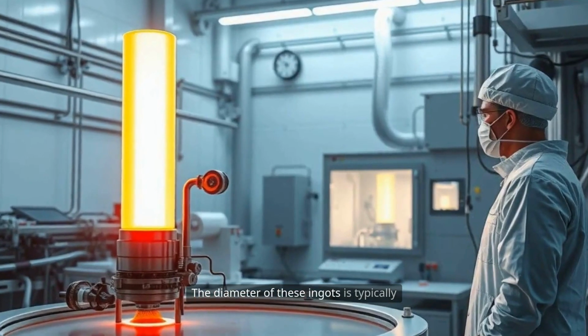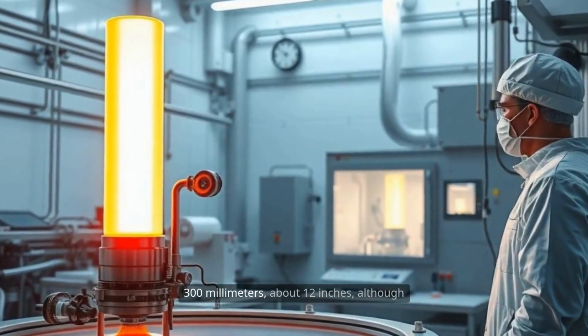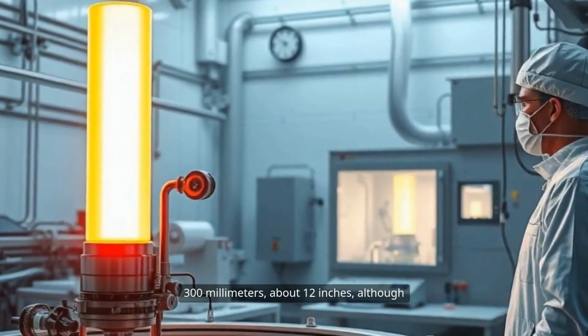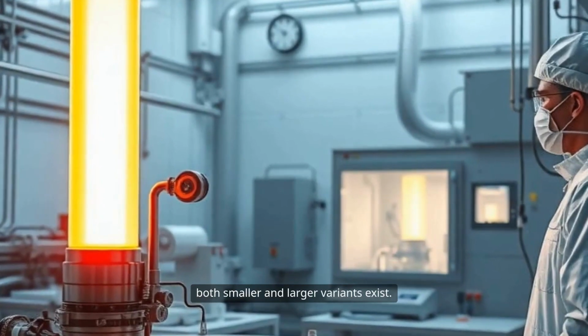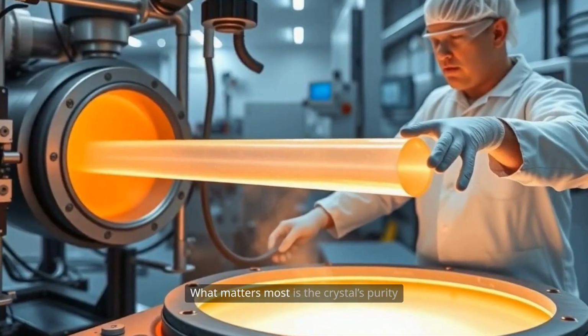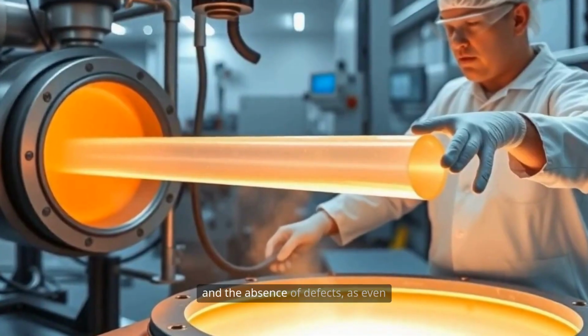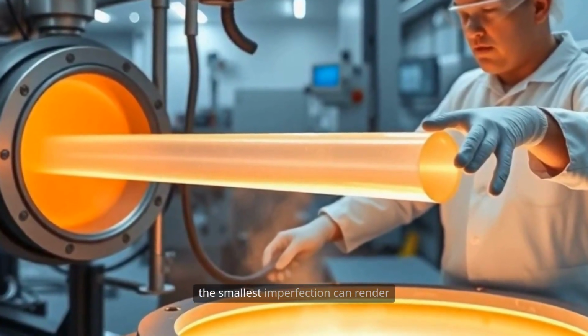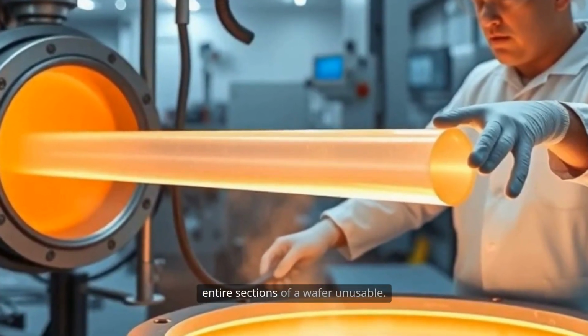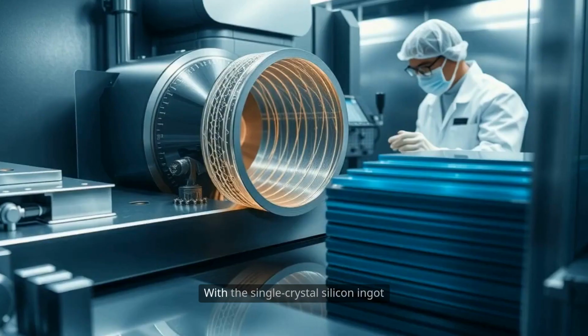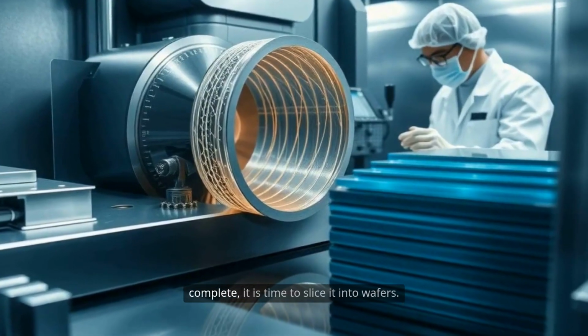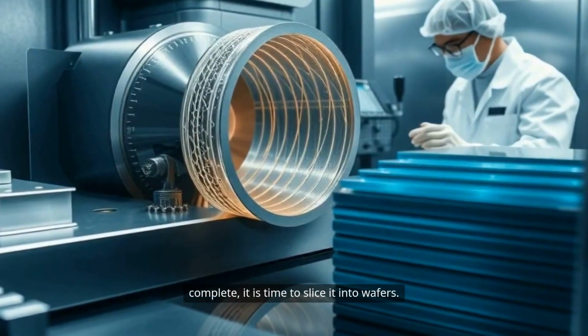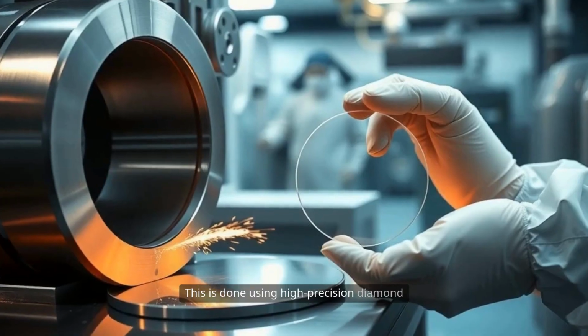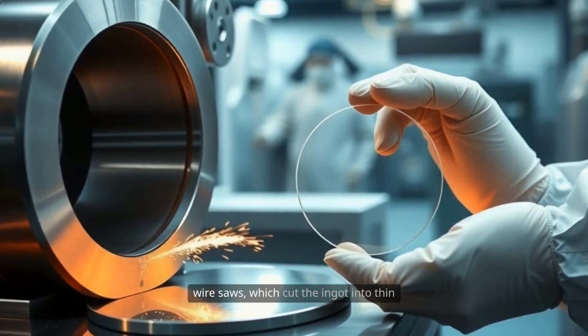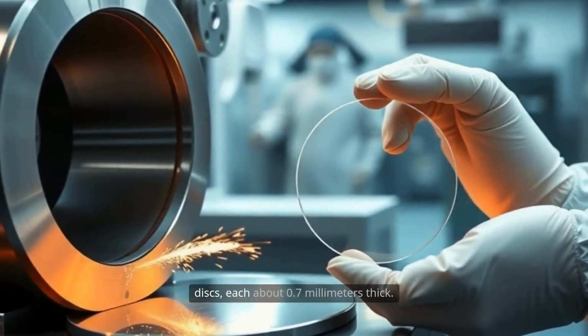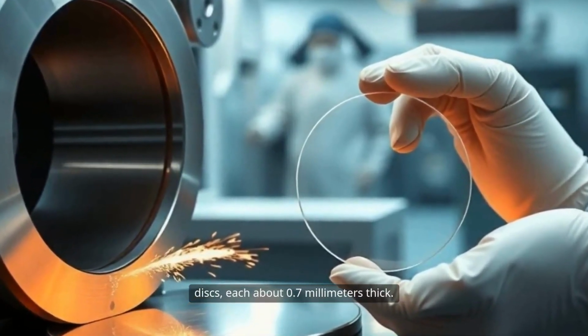The diameter of these ingots is typically 300 millimeters, about 12 inches, although both smaller and larger variants exist. What matters most is the crystal's purity and the absence of defects, as even the smallest imperfection can render entire sections of a wafer unusable. With the single crystal silicon ingot complete, it is time to slice it into wafers. This is done using high-precision diamond wire saws, which cut the ingot into thin disks, each about 0.7 millimeters thick.